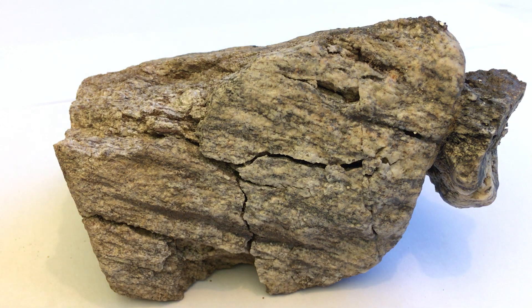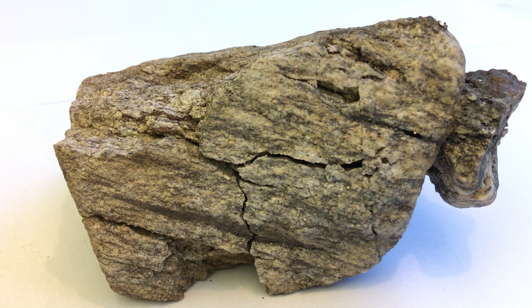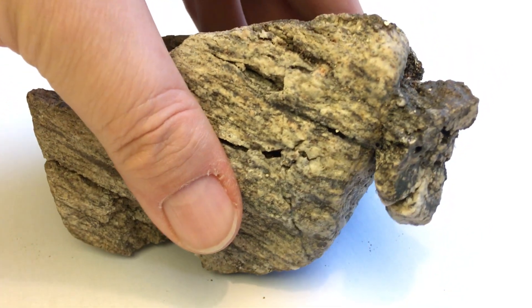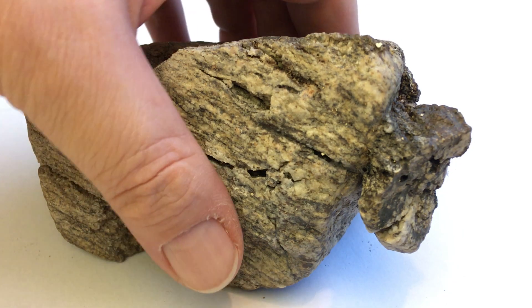Here is some of the larger block material. You can see there is some large cracking that affected the gneiss - this is thermal cracking that happens on heating. Here at the side we see a smaller piece of gneiss that's now attached to this larger piece.